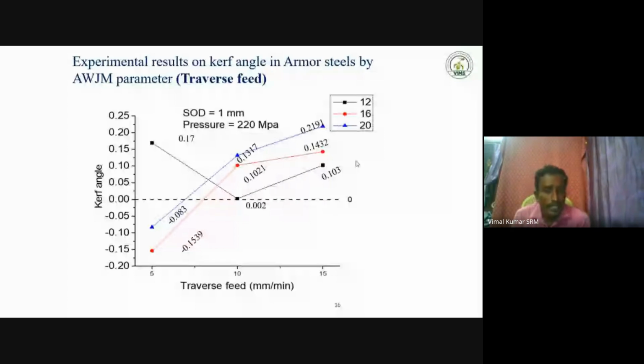From those readings, we can draw the graph. In this graph, we can easily identify that as the traverse feed is increased, the kerf angle also changes. The black line is the 12 mm plate, the red line is the 16 mm plate, and the blue is the 20 mm thickness plate. For all the plates we fix the SOD and pressure, and we change the traverse feed to see whether the kerf angle changes or not.